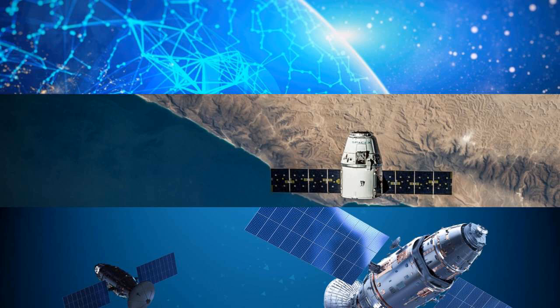So really, our approach is to understand the mission's optical and thermal needs, then adjust the coating's microstructure and thickness to hit the right balance. So that's why the very same technology has already flown on more than 40 missions, each one different, but all benefiting from the fact that these coatings can be customized without sacrificing the durability and space qualification behind them.